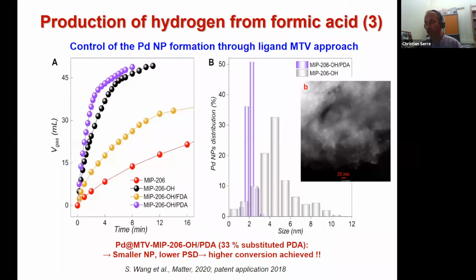And that's exactly what happened, because you see that the particle size distribution when you use the pyrazole functionalized material fits perfectly with the pore size of the MOF, around 2 nanometers in size. So it is really inside the pores of the material. And in terms of catalytic activity, it has an even higher activity than the OH functionalized material, probably because you have better accessibility and better confinement of the species inside the pores. So this is a nice example of engineering functionalization to optimize the catalytic performance of a mesoporous solid.